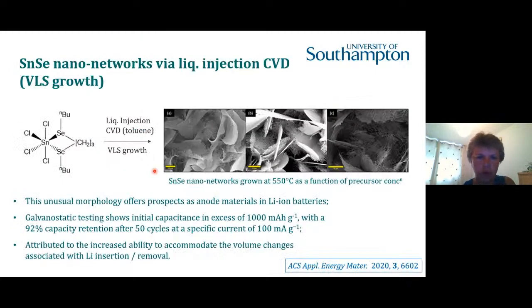And the last example to show you is using, again, the same precursor, but slightly different conditions. Now we can grow these nano networks. So these are like sheets, like thin films, where we've got ribbons which are crisscrossing to create these nano networks. And you can see they differ across A, B, and C in these scanning electron micrograph images. And these are just controlling the growth as a function of the precursor concentration. The morphology here is particularly open. These are really very open structures with not many tins and seleniums in each portion of the structure.